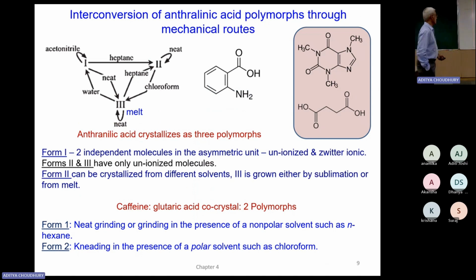All right. Now this slide shows that you can convert different forms, polymorphic modifications, just by grinding in different solvents. That's what I mentioned to you before, because solvent has influence. This is anthranilic acid. It crystallizes in 3 polymorphs. It depends how you do that. You can interconvert them. The structure is shown here. Form 1 has both the unionized one and the zwitterionic. You see what I mean by zwitterionic? The proton is transferred. It is an ammonium salt. This is an acid. Okay, that's zwitterionic ammonium.